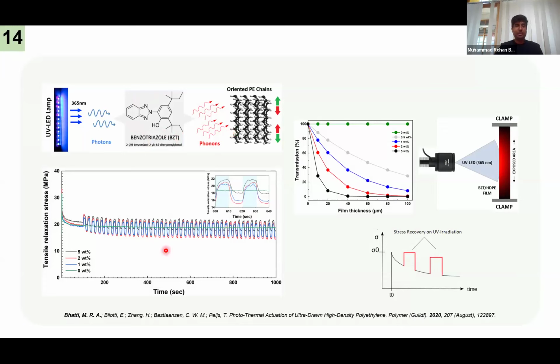We ran a simple tensile relaxation experiment. Usually what happens over here, when the BZT absorbs light energy, it converts into heat, which is available to the surrounding oriented polyethylene chains, that because of the negative coefficient of thermal expansion tend to contract. But because we are running the experiment, we are holding the chain from both ends, and because of the tensile relaxation, the strain remains at a constant level. The only thing that can change is the stress that we call actuation stress.